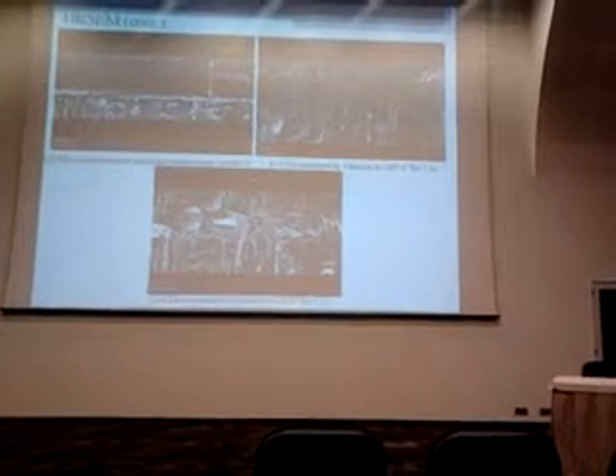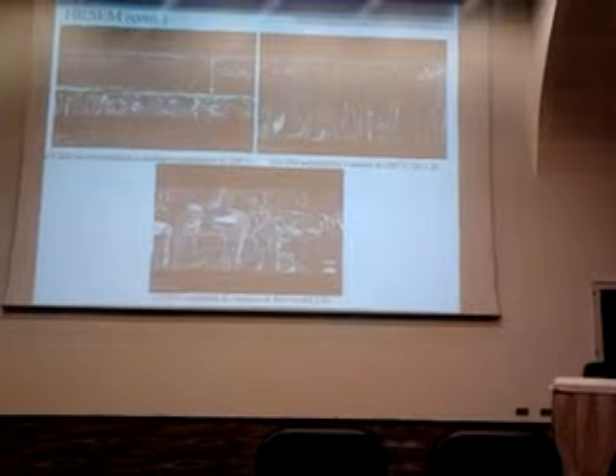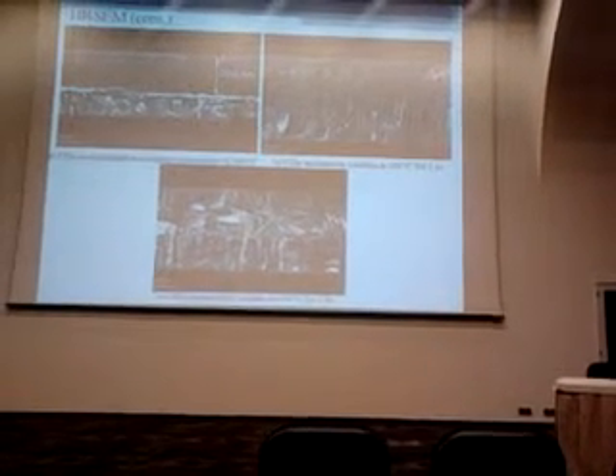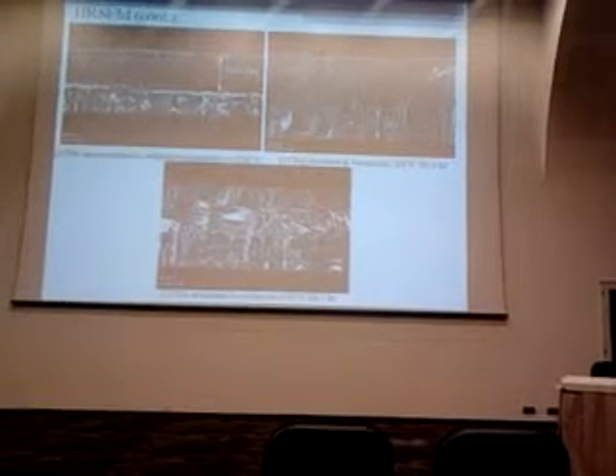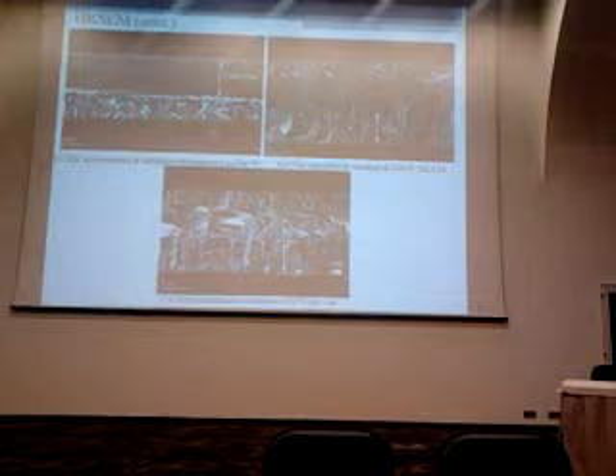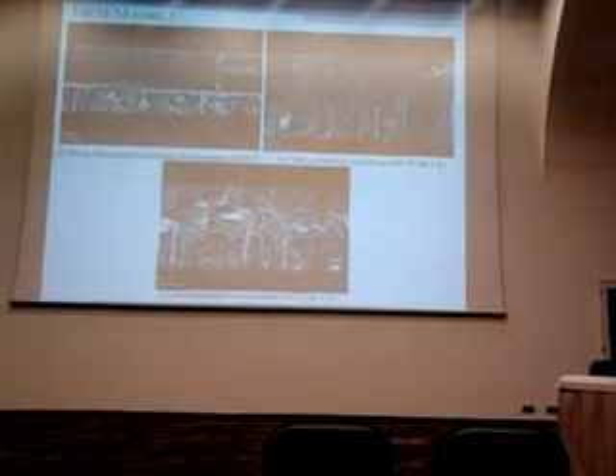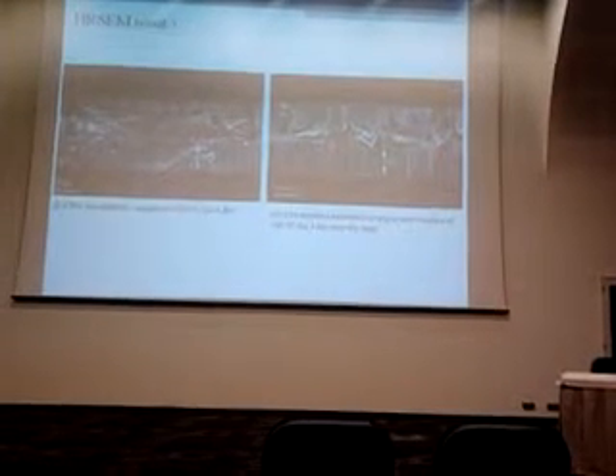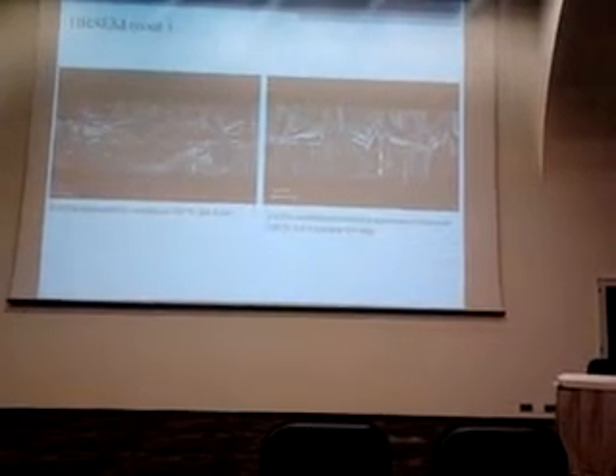We then increased the temperature from 200 degrees centigrade to 500 degrees centigrade. After increasing the temperature to 300 degrees centigrade for 1 hour, the crystal structure doesn't change enormously. But when we increase the temperature up to 450 degrees, the structure changes further, though we can still see two layers. Then we increased the temperature to 480 degrees centigrade for 2 hours, then 500 degrees centigrade, and also applied double annealing.